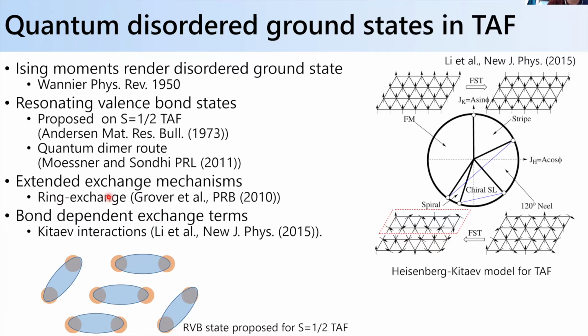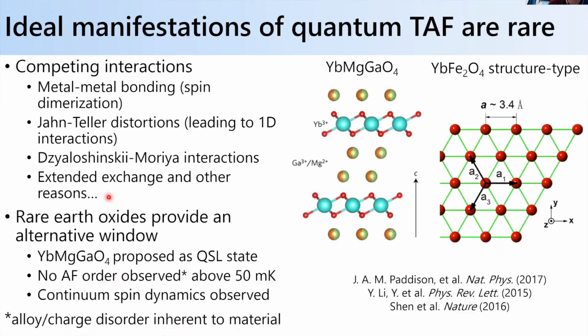But actually realizing these types of quantum ground states on a triangular lattice is, from the materials world, actually kind of difficult, because really ideal manifestations of, we'll say, a quantum triangular lattice antiferromagnet are pretty rare. And the reason is that you're always dealing with other competing interactions in real materials. Oftentimes when you think about creating a triangular lattice of magnetic ions, they're usually in a network of edge sharing octahedra, in which case the magnetic ions get rather close together, and then you can induce things like metal-metal bonding.